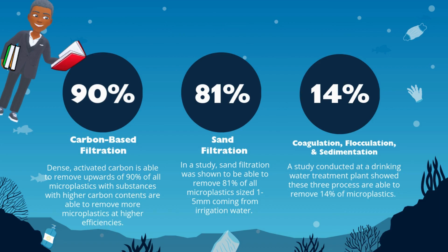And so it can capture most microplastics, and this is because its sand grain sizes are around 0.4 to 1.2 millimeters, and its pores are much smaller than 1 millimeter. And so as we know, they rely particularly on size exclusion to capture microplastics in water samples. However, they are less effective for microplastics that are around 10 to 20 micrometers.